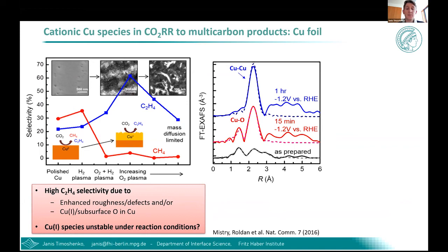In particular, the study by Mistry and others focused on copper foils treated with oxygen plasma and demonstrated that after such treatment, the selectivity of CO2 conversion to ethylene is significantly increased, something that was not observed after treating the foil with hydrogen plasma, for example.